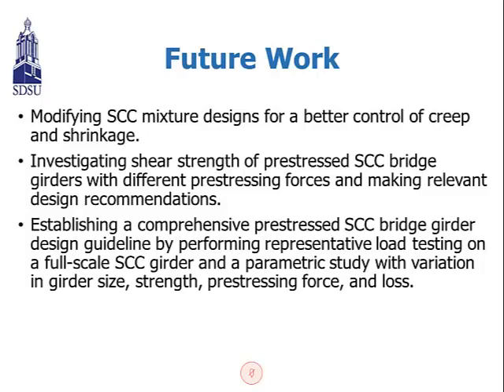Based upon our results and findings, we identified some future work. First, we need to modify the SCC mixture design for better control of creep and shrinkage. Mixture 4 and mixture 9 have substantial creep and shrinkage strain, so we would like to further research and modify the SCC mixture to reduce the creep and shrinkage strain. The second future work is investigating shear strength or post-cracking shear performance of prestressed bridge girders with different prestressing forces and making relevant design recommendations. The reason is there is a lack of information on shear strength of prestressed SCC bridge girders, so we need to investigate that.